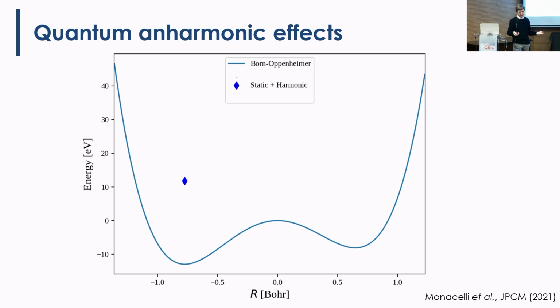We can solve exactly the Hamiltonian with this Born-Oppenheimer potential. The energy we get is this one, okay, much lower. And I put the point here, why? Because if we calculate with that wave function that we calculate numerically the expectation value of the position operator, which is the most probable position where I can find the ions, I get it in this position here, very far from the minimum of the potential, right? Why is this different? Because the zero-point energy is much smaller in this case. So when we add the total energy plus the zero-point energy, in this case it is smaller than when we have it here. So this is what I mean about quantum anharmonic effects, right?